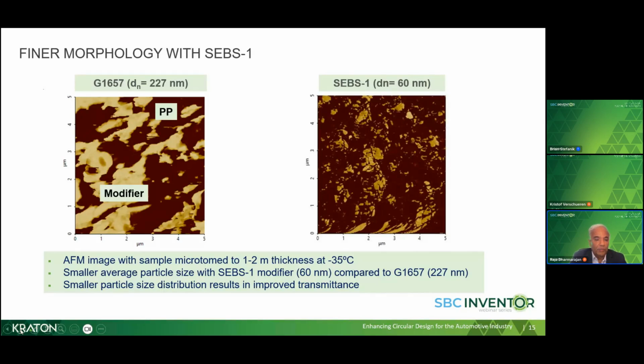So we took multiple sections, and with that, we were able to do an image particle size analysis of the dispersed phase, which is the modifier phase. These pictures are 5 micron across, as you can see here. So when we did the particle size analysis, we found out that with the G1657, we get an average particle size of about 230 nanometers. Whereas when we use our new SEBS1 modifier, we get an average particle size of 60 nanometers. That is almost a 4-fold reduction in particle size. So it is not a surprise that because of the smaller dispersed particle sizes of the modifier, we get better optical properties, namely transparency, which is what we saw in the earlier slide.